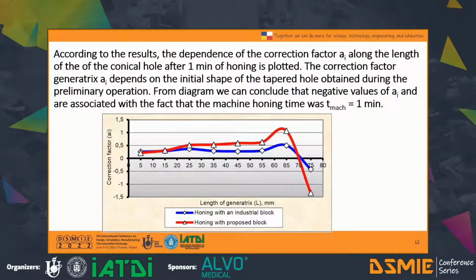The nature of the graph shows the equalization of the correction factor along the generatrix of the conical hole when using the proposed block, which depends on the distribution of contact pressures.